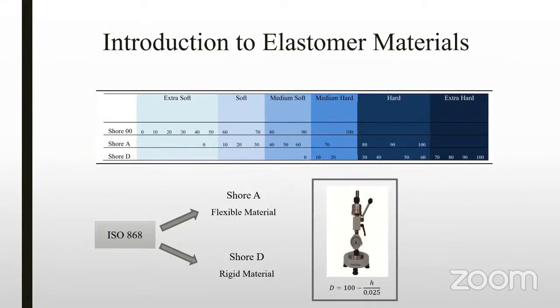The elastomer materials are divided into two groups based on their shore hardness. Shore A for flexible material and shore D for rigid material. The shore hardness of elastomer is calculated based on ISO 868 standard. As we can see in the chart, these materials based on the shore hardness number are divided into different groups from extra soft to extra hard. The elastomer I used in this study is polyurethane in the group of shore A with three different shore hardness numbers, 60, 75 and 85, in three different groups from soft to medium soft and medium hard.